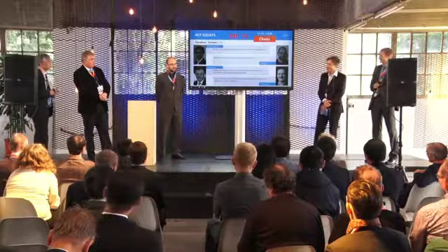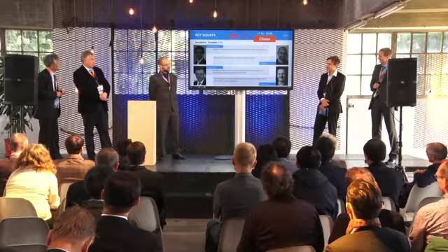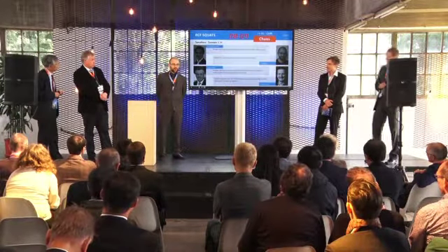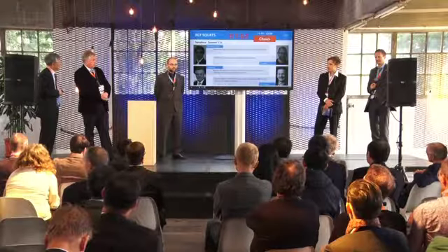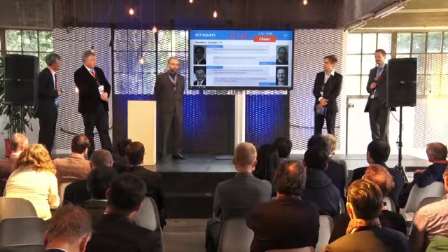Also, with one of the samples, the one that I've done the higher resolution scan on, I believe the initiation on that one was subsurface. So obviously, cracks are working their way up to the surface as you get more mobility as the crack detaches the upper material. So when you're getting subsurface initiation, obviously, you're worrying about white etching layer less, although it obviously is affecting the tribology of the surface.